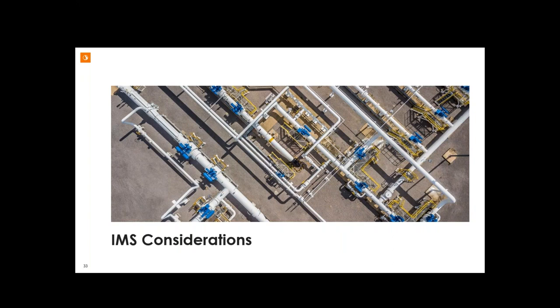Okay, before I move on to integrity management system considerations, I'd just like to summarize that we saw that the crack growth rate is not linear. It's a log-log plot, and it increased about 10 times as our stress intensity increased, as long as above that transition point. That the crack growth rate is influenced heavily even at low partial pressure hydrogen, but it seems to be manageable if we can manage the pressure cycles on a pipeline. Right now we have very good crack management programs. We have a lot of guidance from API RP 1176. And we'll note that the crack growth rate is essentially proportional to the imposed cycles. So we note that pressure cycling is a key operational parameter to keep a close eye on.